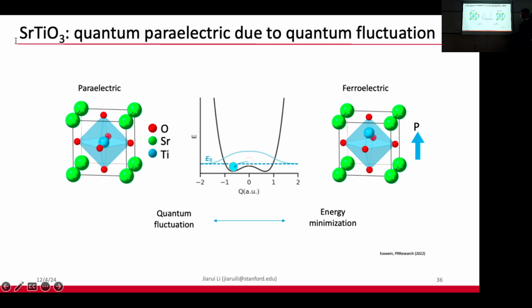However, this motion never happens, even down to 0 temperature, because the quantum fluctuation of the position of these titanium atoms is strong enough to overcome this potential barrier, to delocalize these titanium atoms on either side of the barrier. So there is a competition between these quantum fluctuations and these energy minimization actions.